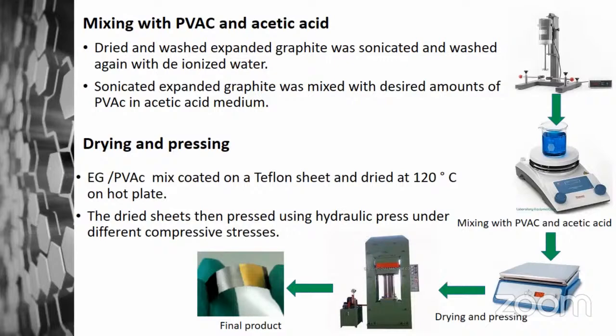In the drying process, we spread a thin layer of PVAC and expanded graphite and use Teflon sheets, because Teflon sheets withstand 120 Celsius, and then we put it on the hot plate to evaporate the acetic acid. After the evaporation, we can take the thick film of PVAC and expanded graphite polymer using a press.